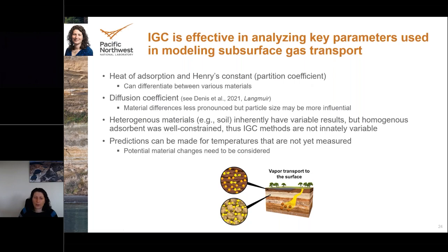And then for diffusion coefficient, I didn't show the results here, but they are captured in our publication from 2021 in Langmuir. Our takeaways from the diffusion coefficient, one was that diffusion coefficient increases with temperature. Another was that the material differences were less pronounced between just looking at soils on different materials, but that particle size may be more influential on diffusion rather than the specific type of material.